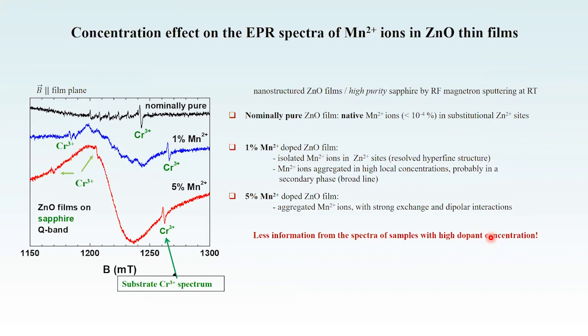In thin films: in a nominally pure film, except for the native manganese ions giving a hyperfine signal, we observe another signal present in all samples, coming from the substrate. Although we use high-purity substrates, EPR was able to detect impurities at ppm concentration — so we can still call them high-purity substrates. By increasing dopant concentration, we observe an increasing broad line due to aggregated manganese ions. Therefore less information can be obtained at high concentration.